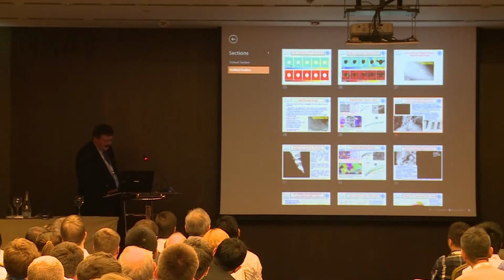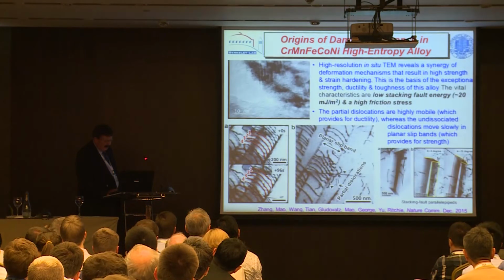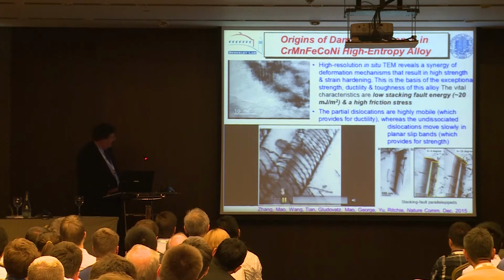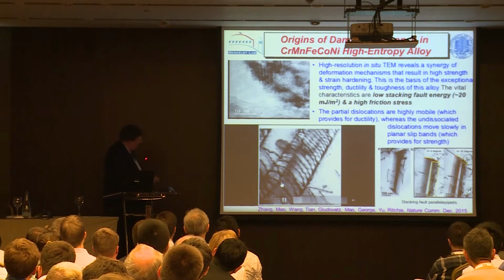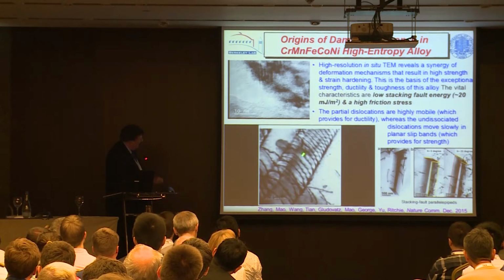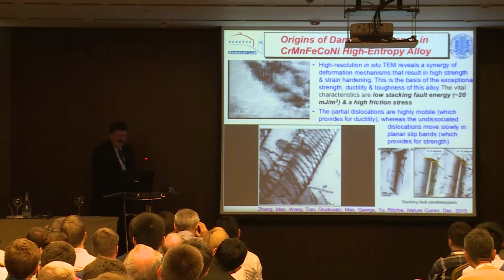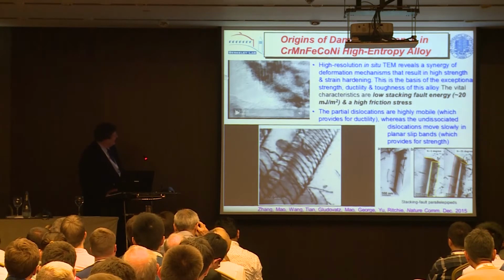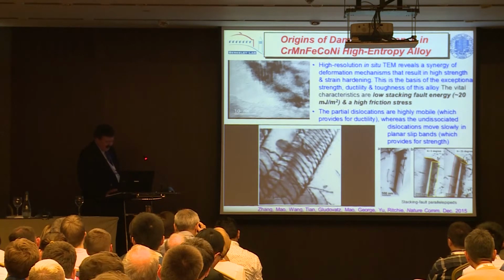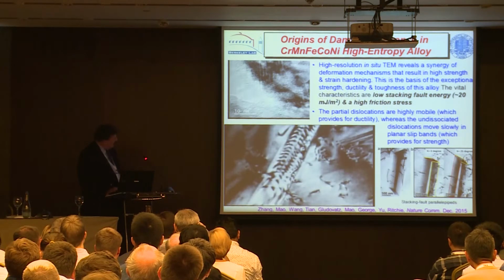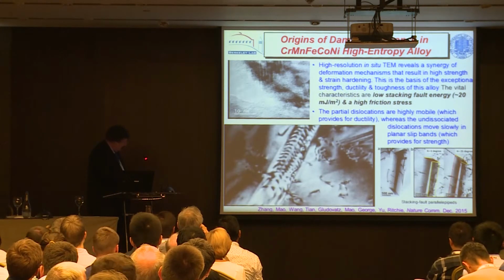You see these long planar slip bands where the undissociated dislocations move in very tenuous fashion, yet you also see this very rapid motion of the partials. I'll give you an example here. This is that same slip band, and I'll stop the movie in a minute.